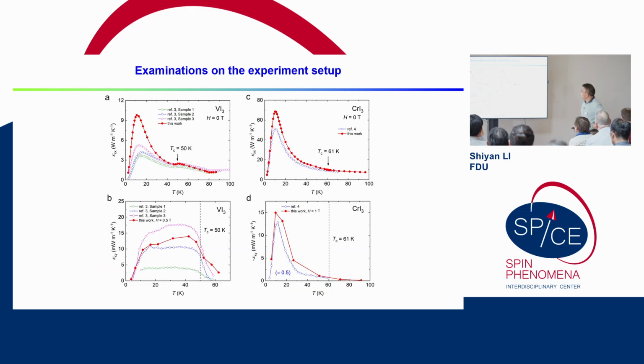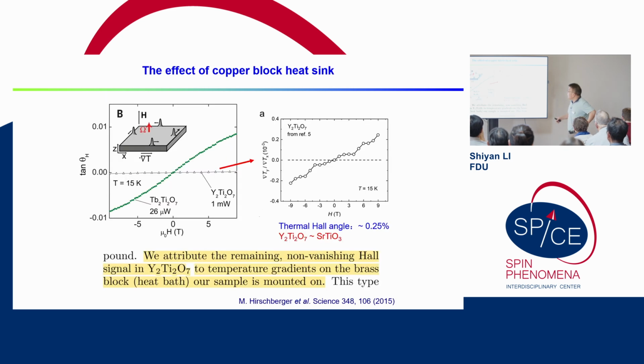So after all these checks, now we are confident that indeed we discovered this universal phonon thermal Hall effect. Since we claim that this thermal Hall effect is universal for all crystals, we try to look into the literature. Is there some negative report that you measure a single crystal and there's no thermal Hall effect? As I said, in this Science paper from Professor Ong's group, they observed this large thermal Hall signal in this quantum spin ice, but for another non-magnetic one, Y2Ti2O7, they actually observe some small signal, but we attribute the remaining non-vanishing Hall signal in this compound to temperature gradient on the brass block. So they thought this is not real.